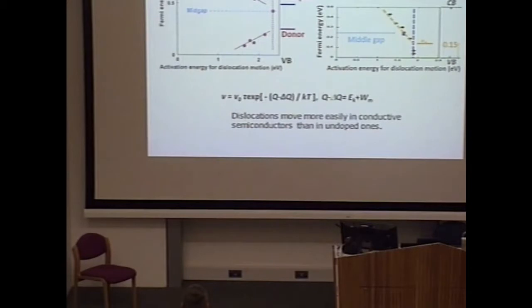And this is a silicon case, and this is a germanium case. So in the silicon case, the activation energy for dislocation motion changes like this depending on the Fermi energies, and undoped crystals are here. So from this figure, we can determine that dislocations have some acceptor levels and also donor levels. And in germanium cases, only an acceptor level appears.